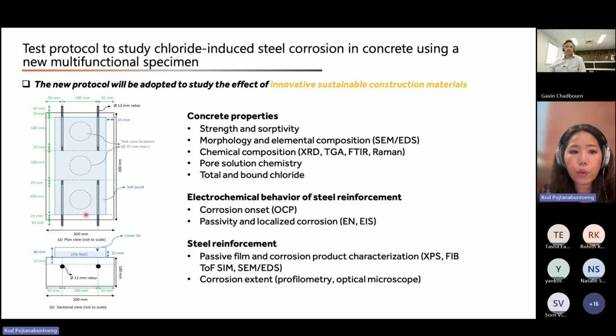The idea is that we will go in at intervals and monitor the onset of corrosion through open circuit potential, passivity, or localized corrosion, using the electrochemical noise or the impedance with the rebar. Once we notice changes in electrochemical activity, demonstrating either passive film breakdown or active corrosion, we can remove the test sample and do the coring in the circle. The dashed circles here are the areas dedicated to coring afterwards, to verify that activity from the physical and chemical perspective in terms of chloride diffusion. The cross section of this area can also be taken to look at the actual corrosion or the damage on the passive film on the reinforced bar. So this protocol or test sample will enable us to support the model that we are developing.